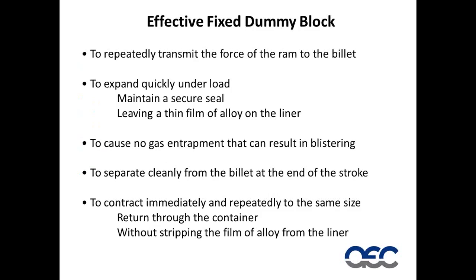An effective fixed dummy block needs to do several things. Number one, we want to repeatedly transmit the force of the ram to the billet. Number two, it needs to expand quickly under load. In most cases, we're looking at our dummy block to mechanically expand about 30 thou in diameter. We want it to maintain a secure seal with the container so that no aluminum passes by. And we would like to leave a uniform thin film of alloy somewhere around 8 to 12 thousandths thick on the ID of the liner.